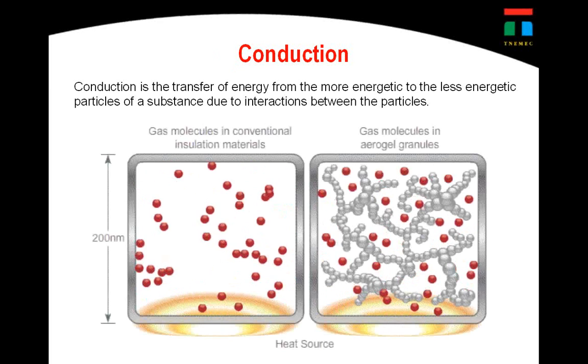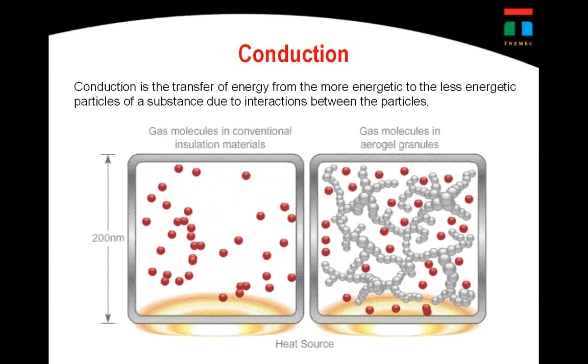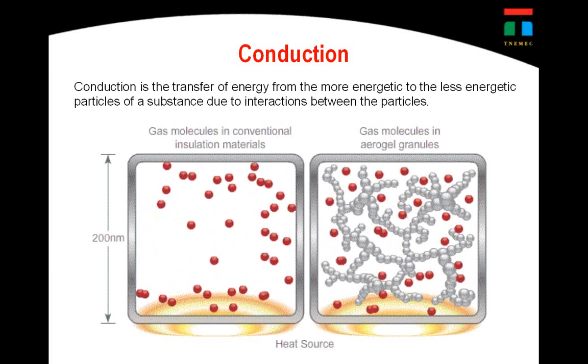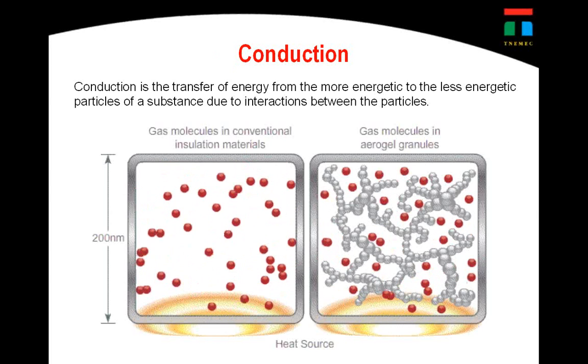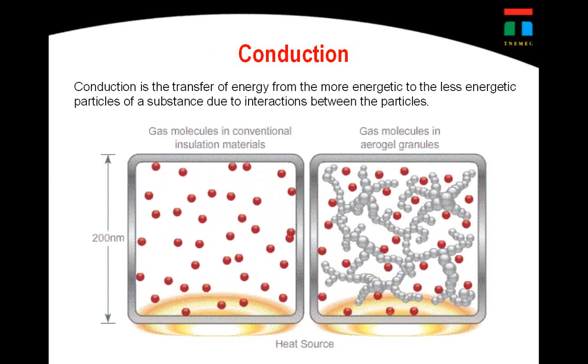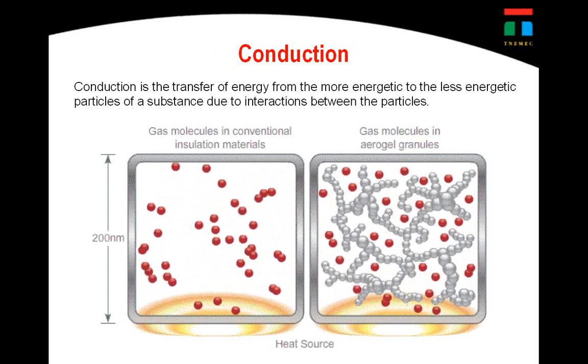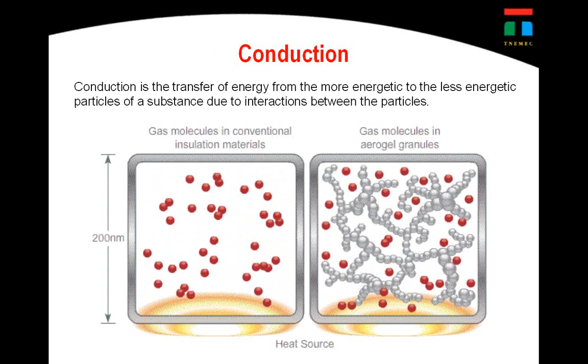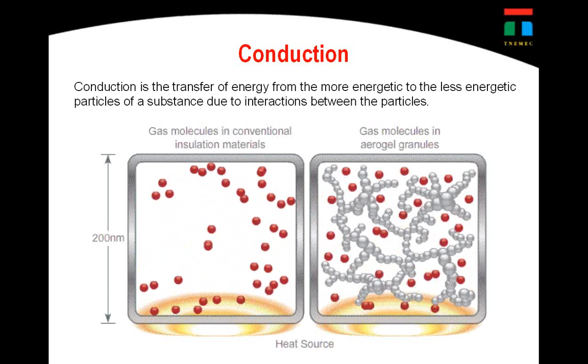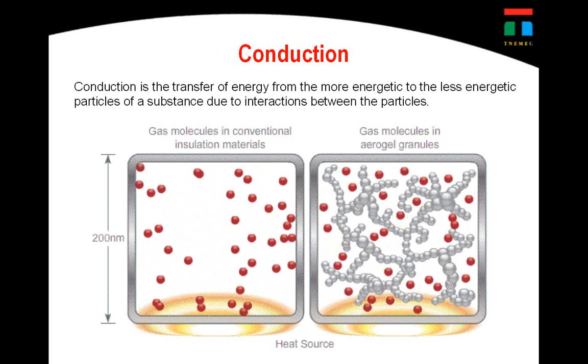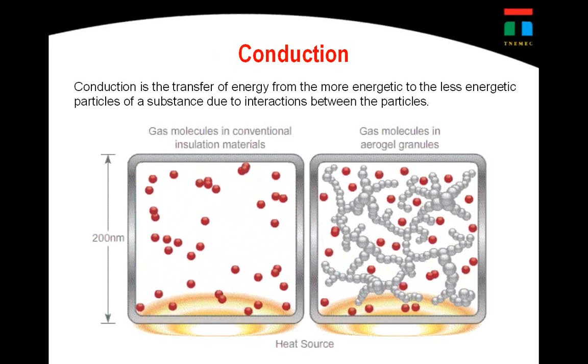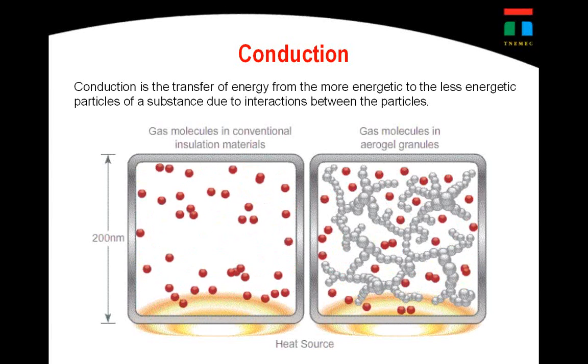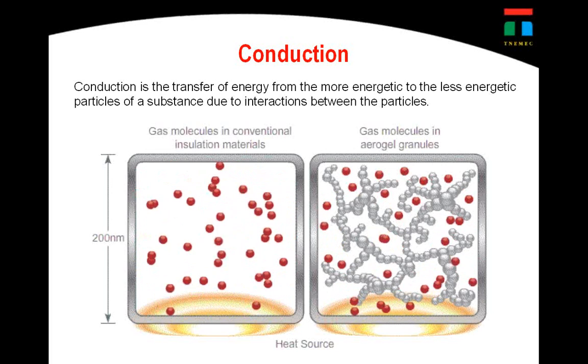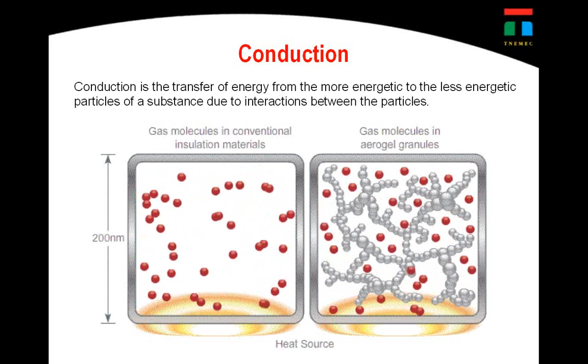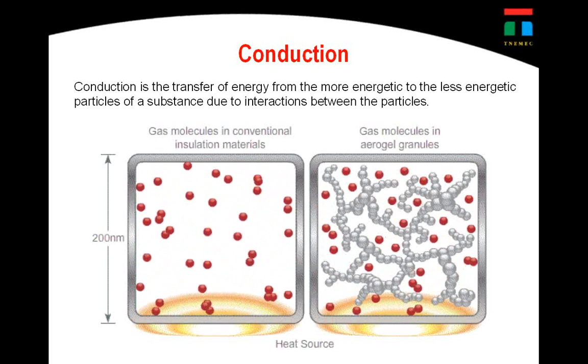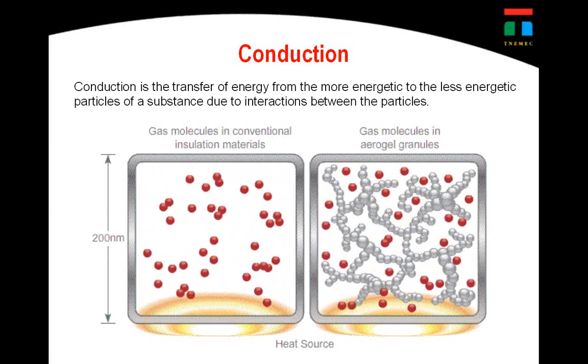And I think this is a really good slide that kind of illustrates what we're talking about. So here you have gas molecules in a conventional insulation on the left. And you're looking at something that's 200 nanometers in depth. So if I have 200 nanometers of insulation, this is what the air molecule speed would be mimicking in that particular environment. So I have lots of air gas molecules moving around. So when I put my hand on the top of this piece of pipe or this structure, I get a very fast transfer of heat. I get burned, or in a lot of cases, I'll get cold if it's very cold.